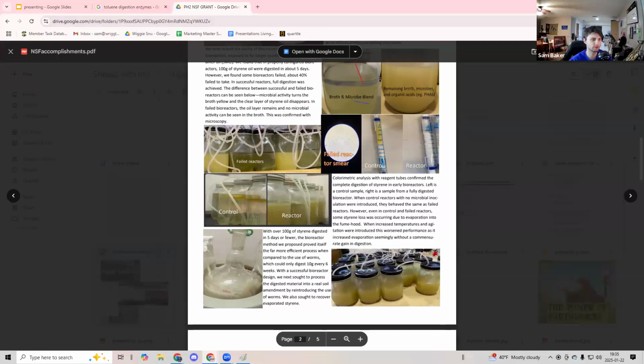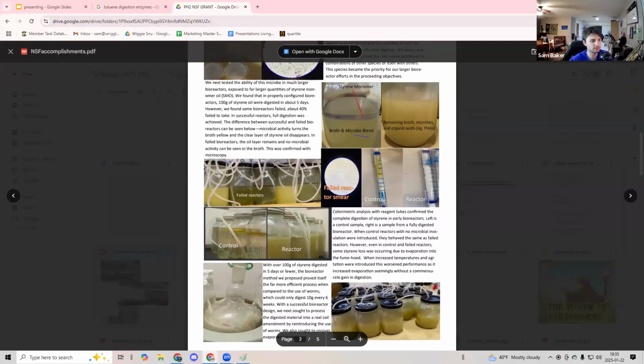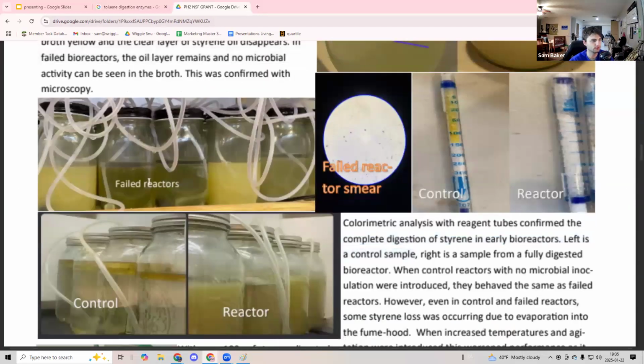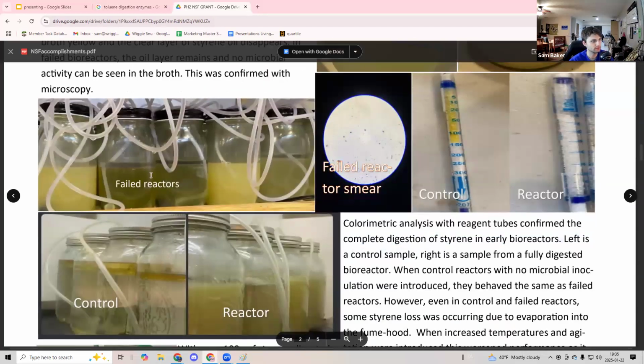And I've actually got a much better picture of it here. But you can see in this picture some successful reactors and some failed reactors. These guys over here are the bioreactors where the microbes were not inoculated correctly. The styrene layer, the layer of plastic, essentially on top of the liquid, remains. Whereas those where they were inoculated with the microbes, the plastic layer is gone. So that layer is being clearly digested.